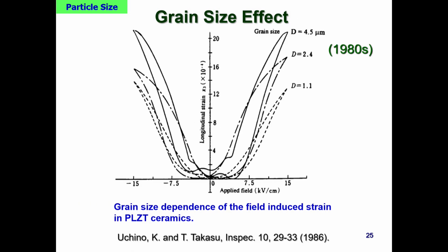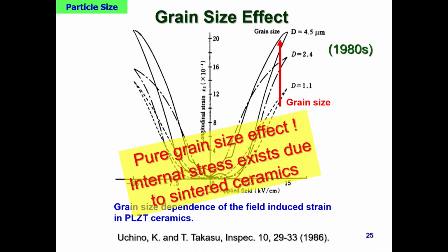Therefore, after getting into the 80s, our group utilized PLZT and made different grain sizes beautifully by changing just the sintering temperature. No, sintering time, okay? And with increasing grain size, you can easily find that the displacement dramatically increases. So a pure grain size effect was observed, but still, in sintered materials, internal stress exists due to the sintered ceramics. So we tried to make separate particles to determine the ferroelectricity.